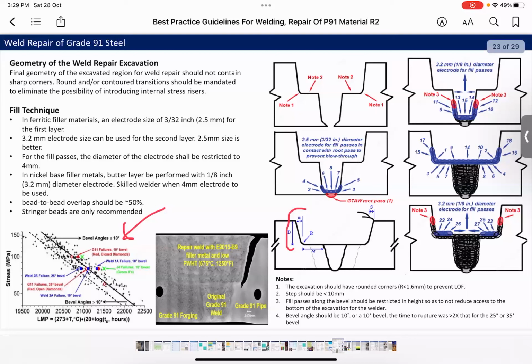So this is the first one, and the second point is regarding the width of the step bevel. It should be at least 10 mm. It should not be less than 10 mm. According to the recent publication of API 582, it should be 13 mm or half inch. And the bead sequence or the filling should be from the bevel side to the center of the weld.